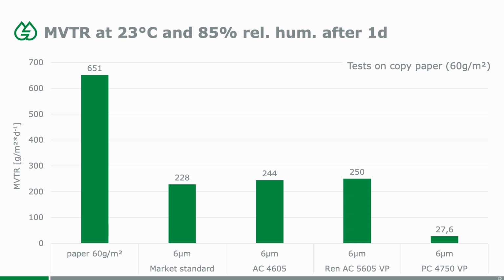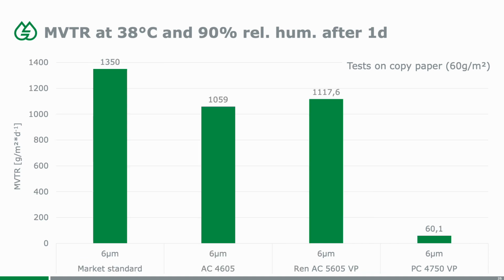The market standard, the AC 4605 and the REN AC 5605, they perform pretty similar. And on the right hand side, you see the PC 4750 outperforming everything with 27 grams per square meter per day on the very poor substrate copy paper with 60 grams per square meter. So that's a very, very good result. And now we will go to harsher conditions.